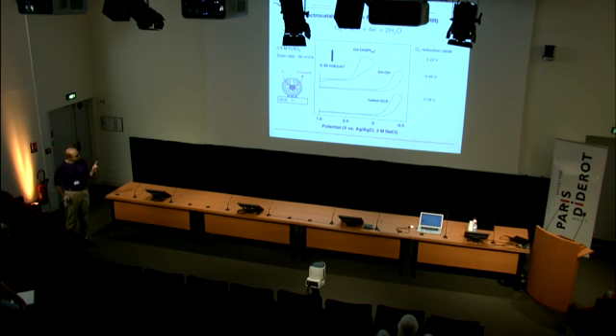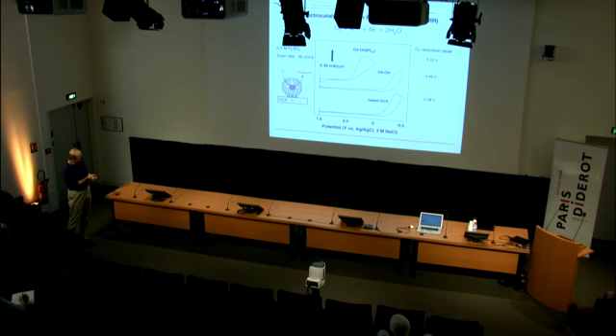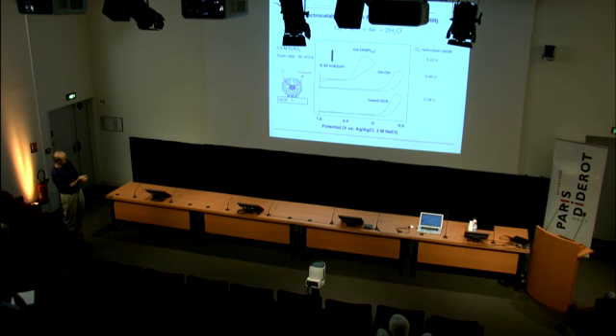Now, I'm showing you this nanoparticle in the center of the dendrimer. Actually, we know that it's an ensemble average, and they're not actually in the center. They're distributed symmetrically in this region of the dendrimer. So they're, on average, a little bit off-center, but near the center. But some, I'm sure, are over here on the side. Some are right in the center. Distribution of sites. So the electron has to be able to tunnel from the electrode up to the nanoparticle, and oxygen needs to permeate through the dendrimer, encounter a clean spot on the surface of the nanoparticle, and then whatever product, peroxide or water, is made has to be able to leave.